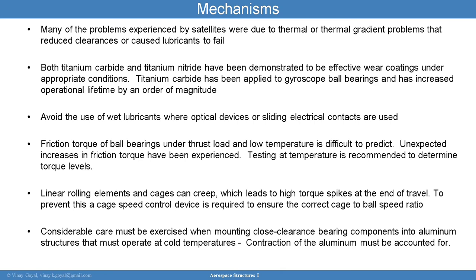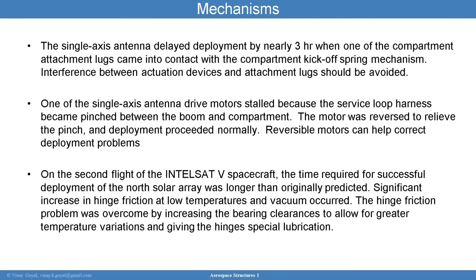Considerable care needs to be used when you're mounting a close clearance bearing component into aluminum structures that must operate at cold temperatures. You want to account for the contraction of the aluminum. Single axis antenna deployment was delayed by nearly 3 hours when one of the compartment attachment lugs came into contact with a compartment kickoff spring mechanism. Interference between actuation devices and attachment lugs should be avoided.